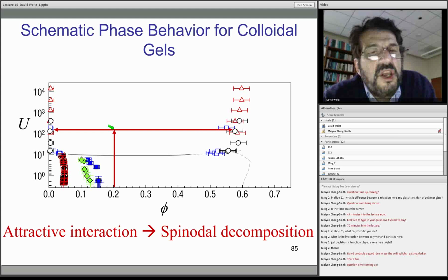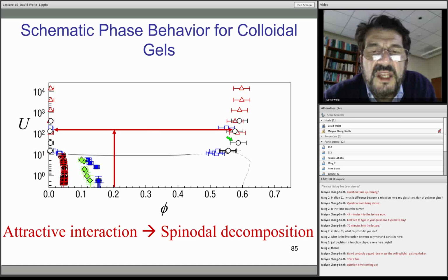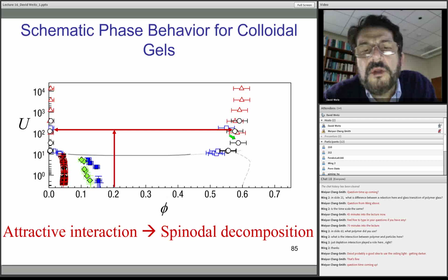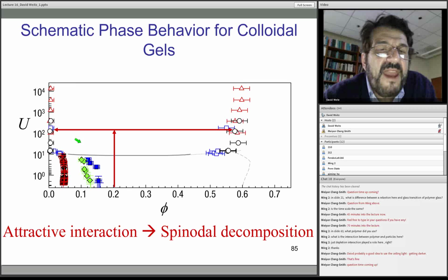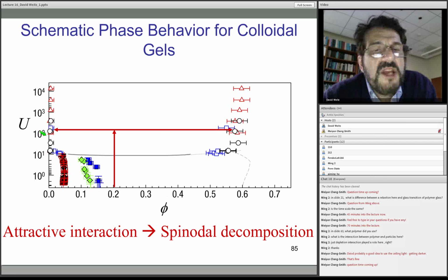to the gelation. You get this region where it's very poor in colloids, almost no colloids, there are very, very few monomers, and the second region where it's very concentrated. And in fact, if you measure the concentration in this very concentrated region, the local concentration is that of a colloidal glass. So what you're doing is you're phase separating. The gelation is due to a phase separation, a non-equilibrium spinodal phase separation.